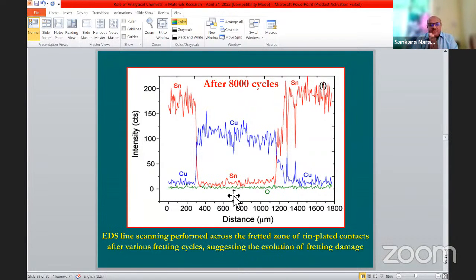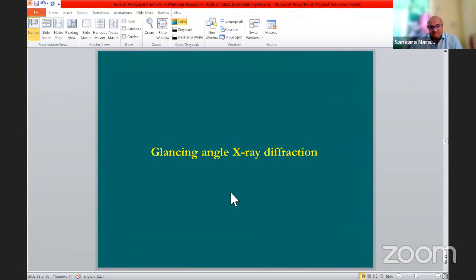If there is a small vibration in the motor vehicle, that will lead to a small amount of fretting, which removes the tin metal and then leads to the formation of tin oxide, which is poorly conducting. Automatically your electrical contact becomes very poor, the connector will fail, and your dashboard will not show the indicators properly. So this is the problem with fretting corrosion. I've explained some of the analytical methods and how they can be used to understand the mechanism of the problem.